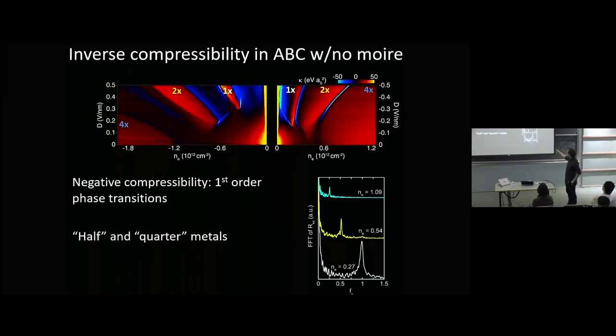If I then cross this first order phase transition and measure quantum oscillations in this phase here, I get a peak at 1/2. That's what I showed you before. This whole phase has 2-fold degeneracy rather than 4-fold. And if I keep lowering the density, I get a peak only at 1.